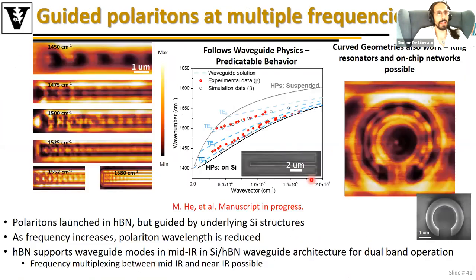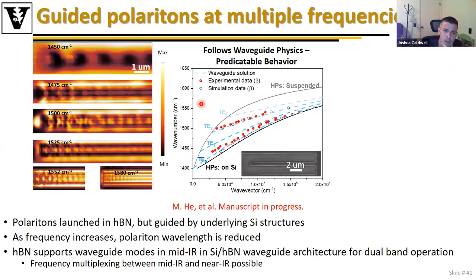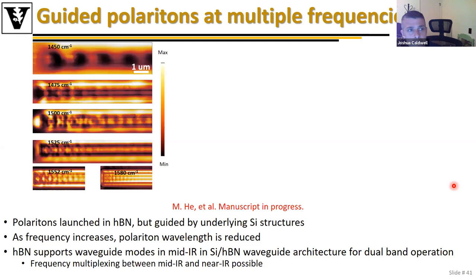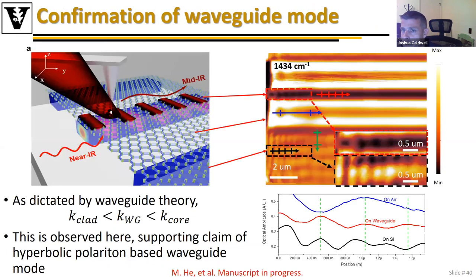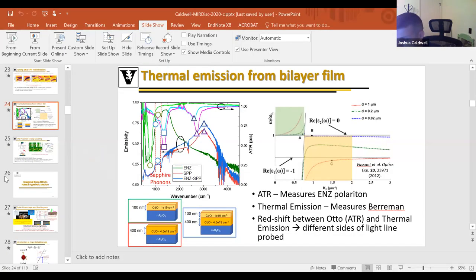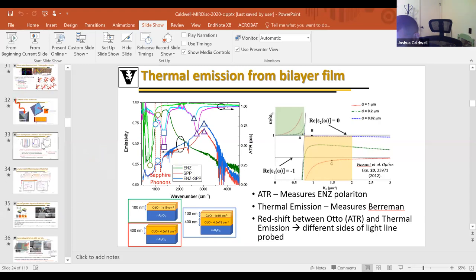How to estimate momentum of hyperbolic phonon polaritons in the nanopattern analytically? I guess the question is, are we talking about this work here or localized resonances? If we're talking about the waveguide physics here, this is just using a simple waveguide model, but now incorporating the permittivity of the boron nitride and the permittivities of the underlying silicon and suspended air. I didn't get to spend too much time on this. Let me transition between slides this way. Hopefully you can still see my screen. Yes. Okay.